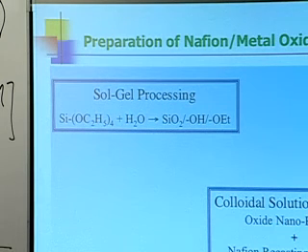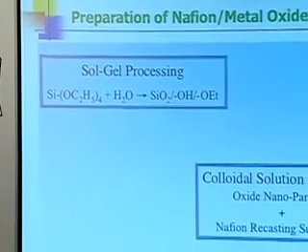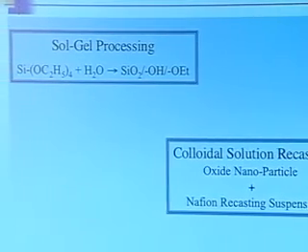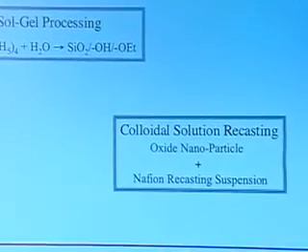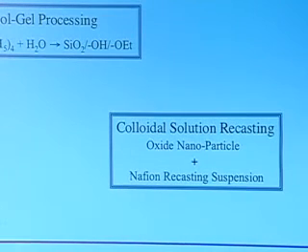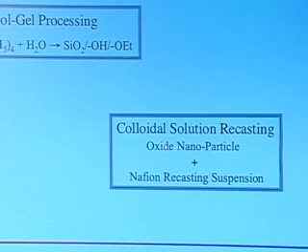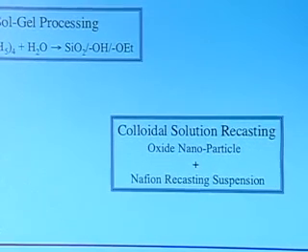This, when we started, was supposed to be a really bad idea. It sounds like a bad idea on paper because, well, this thing sounds nice and homogeneous, and you have some kind of interesting material. This sounds like a big mess, and why would it give you an interesting material? And there were some preliminary experiments that would have suggested it was a big mess and didn't give you nice materials. But if you go down to, say, tens of nanometer particles, and you do this, in fact, you get a very homogeneous material, and it works as well as this material.